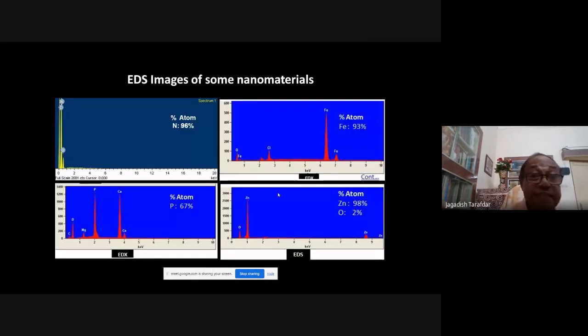Now, this is EDS that I am telling you. This is also a very important instrument for the industries. You see, we find that our nitrogen nanoparticle which we are preparing is 96% pure, iron 93% pure, phosphorus only 67% pure, zinc is 98% pure. So from this EDS, you may measure the purity of your particle. So that is also a very important instrument.